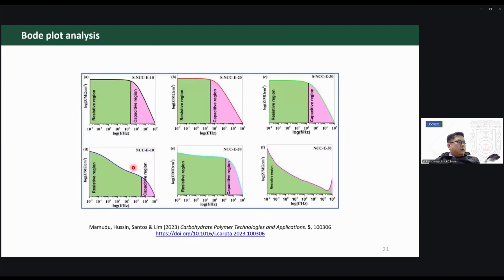And here, we also look at the Bode plot. The Bode plot is quite important because it tells you something about the delamination and the damage which can happen to the coating. So delamination and damage are the primary factors that contribute to coating failure when exposed to a corrosive solution.